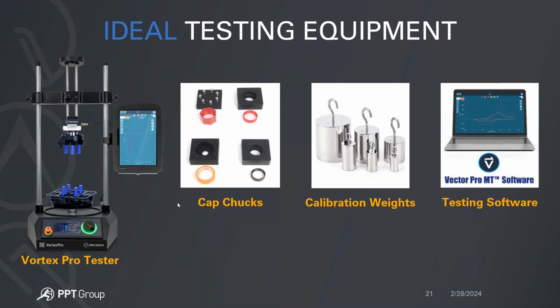And that also generates consistent results, which allows you to set whatever your testing parameters are for pass and fail, and easily identify the samples that are passing and the ones that are failing. The components will include the Vortex Pro tester, the calibration weights to simulate the axial force, and also the cap chucks, which are more often than not custom made to fit the actual caps. The reason for that is so you have the flat bottoms that allow you to apply that axial force. For almost every CRC test we do, we end up coming up with customized chucks to fit the particular cap on each unique sample.